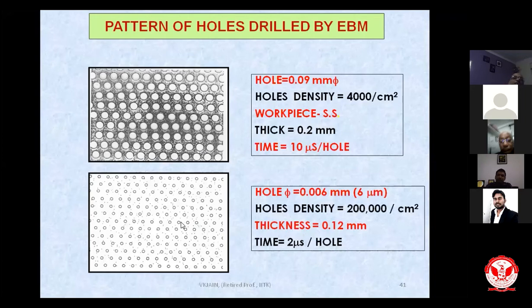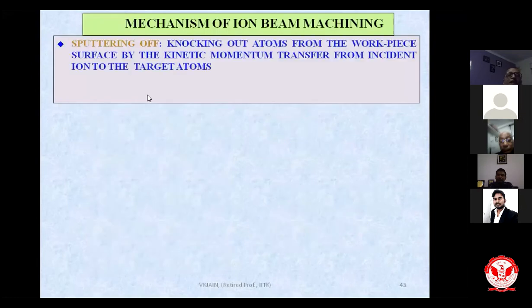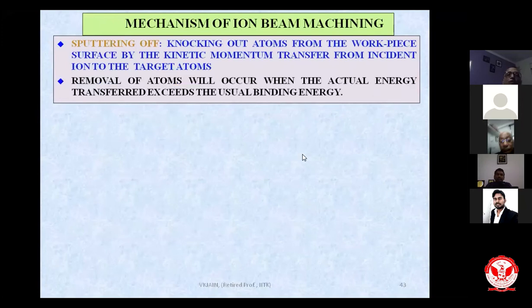So you can see the kind of capabilities with electron beam micromachining. You can make many required components with this particular process. Ion beam micromachining, I have explained to you the mechanism. It is known as sputtering off, that is, knocking out atoms from the workpiece surface by the kinetic momentum transfer from incident ion to the target atoms. Removal of atoms will occur when the actual energy transfer exceeds the bonding energy of the atoms. Now, this I have explained to you directly.